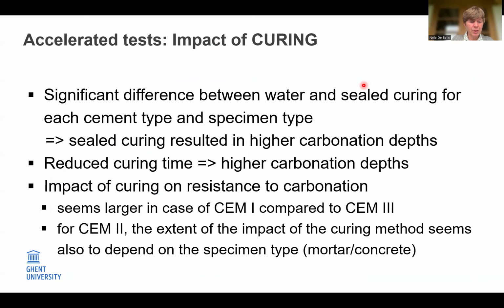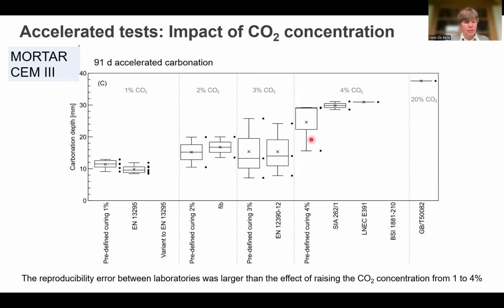Regarding the impact of curing, we found a significant difference between water and sealed curing, with sealed curing resulting in higher carbonation depths, and as expected, a reduced curing time resulted in higher carbonation depths. Unexpectedly, the impact of curing on resistance to carbonation seemed larger in the case of CEM I compared to CEM III. In these results of accelerated testing, you can see a trend that the carbonation depth increases with increasing carbon dioxide concentration. But actually, the reproducibility error between the labs was so large that this effect was not significant.